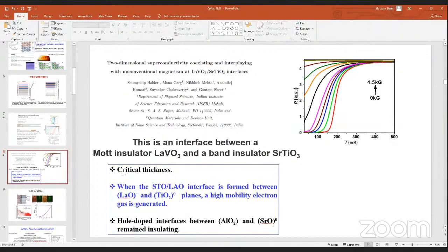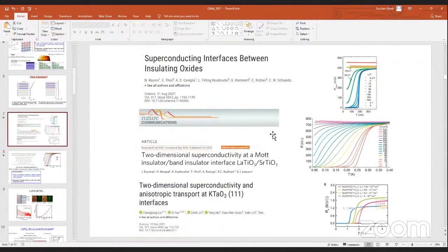Okay, so I am not denying that the superconductivity is coming from STO, but the entire STO substrate is not becoming superconducting. Superconductivity is coming from the STO side of the interface, number one. Number two, it's not that you deposit anything on STO and it will give you the superconducting phase. So far, it has been found that a superconducting phase is obtained only for three systems: LAO STO, LTO STO, and in our case, LVO STO.